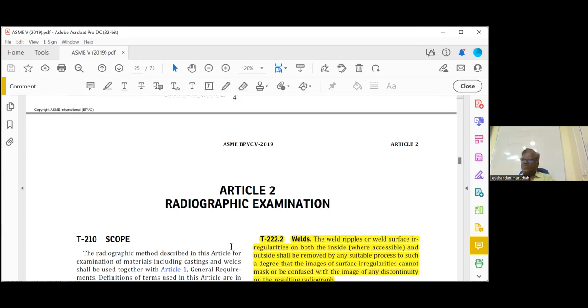As per Section 5, PT, MT, or UT, these three require a procedure and procedure qualification. RT requires a procedure, but does not require procedure qualification. So as per Section 5, for RT there is no essential, non-essential variable table. But for PT, MT, UT, we have essential and non-essential variable tables. Point number 1, about the procedure. Is it clear? So which NDT method does not require procedure qualification? Answer is radiography testing.